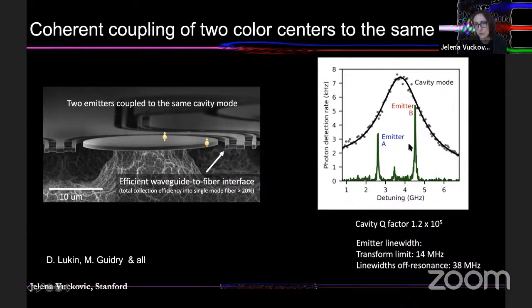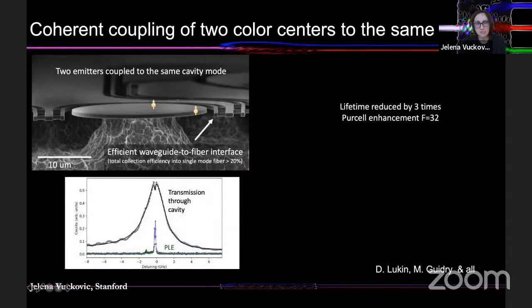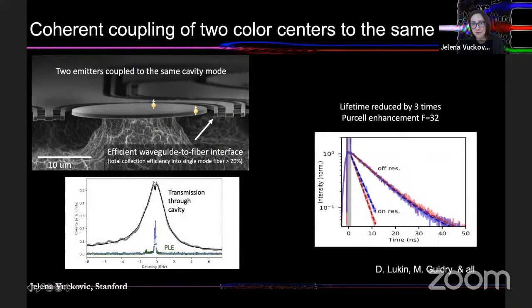So there are two color centers within a cavity resonance. We can measure transmission through the cavity, see dipole-induced transparency. We're not in the large cooperativity regime, but we're approaching cooperativity of 1. So we're starting to see transitions also in transmission induced by these color centers. We also see significant reduction in lifetime and good Purcell enhancement for both of these color centers independently.